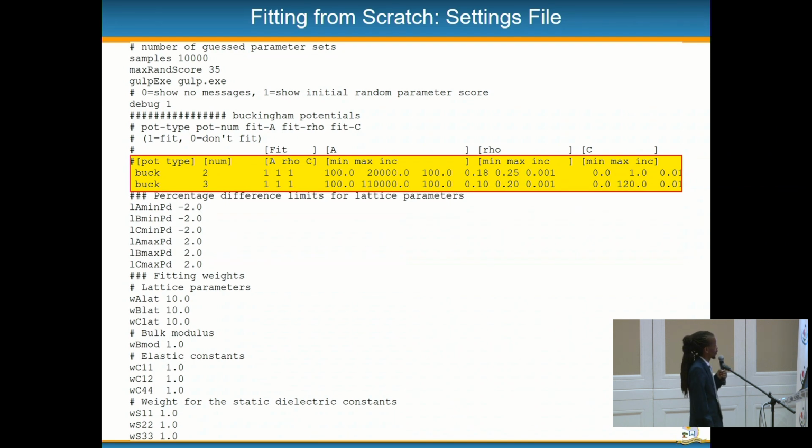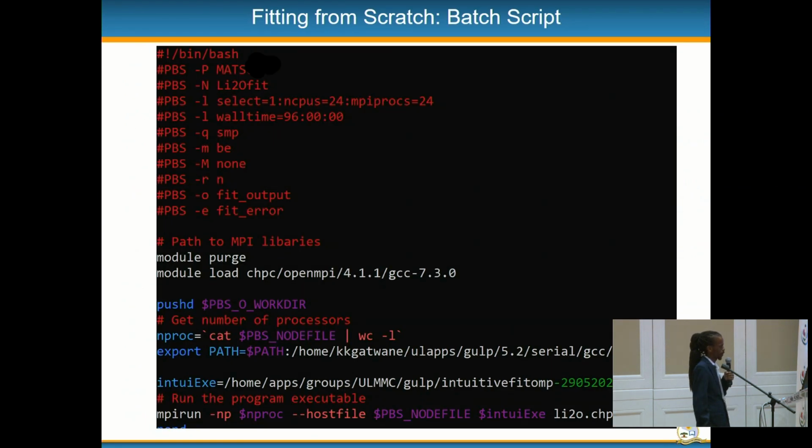Like if you get scores that are like 900, that could mean that there's something wrong with your GULP input file, or maybe your properties are not that good or are incorrect. We once got values like that when we used properties for a different system. And of course, you can actually set weights if perhaps one lattice parameter is not giving the correct value.